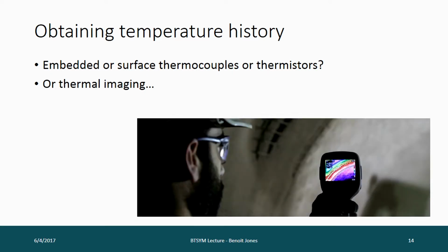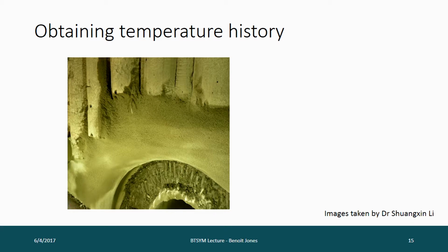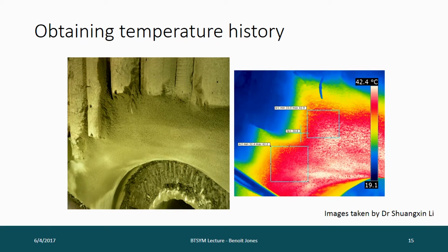So the answer is thermal imaging, of course. With a thermal imaging camera, you can measure the temperature of the surface of the concrete pretty accurately from a safe distance. And you can scan the whole lining without getting in the way of construction operations. So here's a look at some shotcrete, and this is what it looks like in a thermal imaging camera. And you can even, using the built-in software on the camera itself, select areas and get average temperatures of areas, and that's probably better than taking point measurements, because with point measurements you might be susceptible to something sticking out from the shotcrete that has a lower temperature, for example.